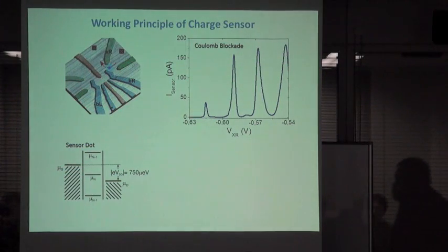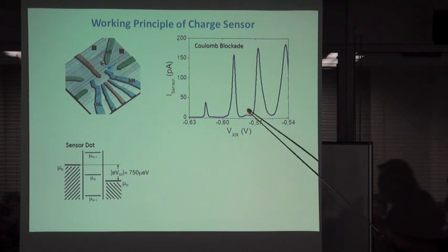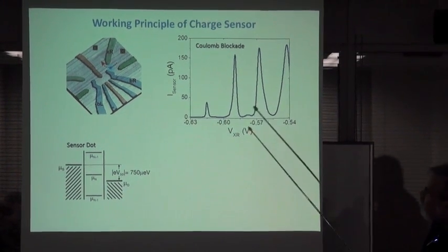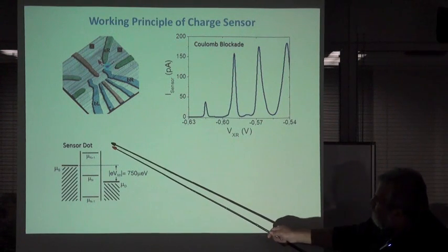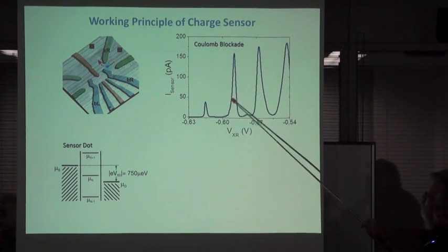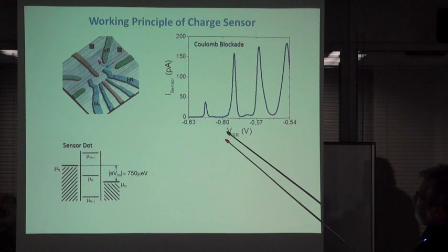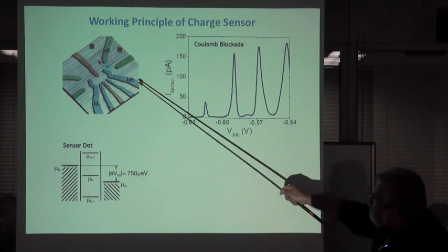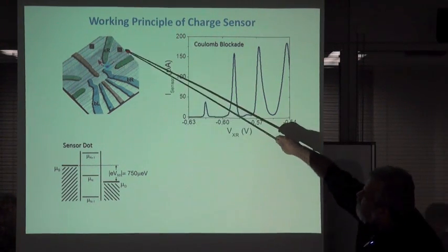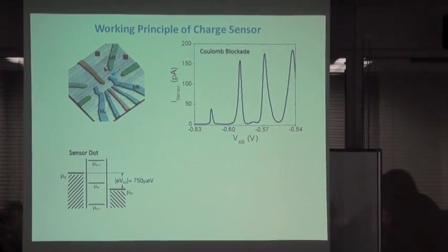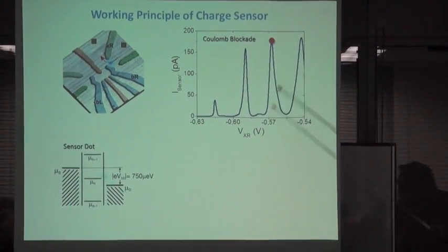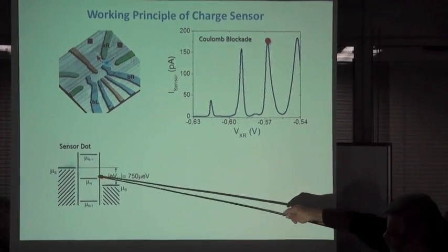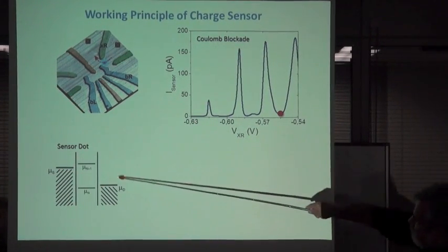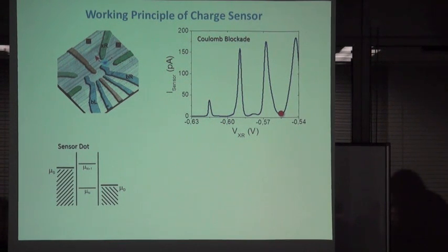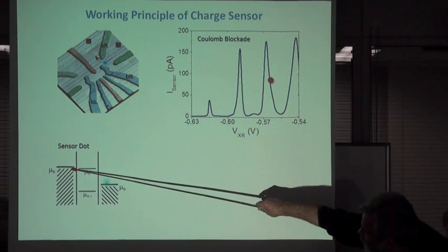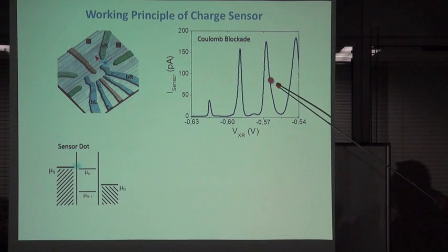Now typically this is more tutorial, but this is real data from such a device on silicon. So this is what we do when we sense such a dot. These are the Coulomb blockade peaks when we have some voltage on the right bias, and we measure, for example, this sensor here. This Coulomb blockade peak we use like this: when we are on top, we have a lot of current through. When we are in between here, we have no current, it's blocked. And when it's just starting, very few electrons can go over. We have an intermediate current.